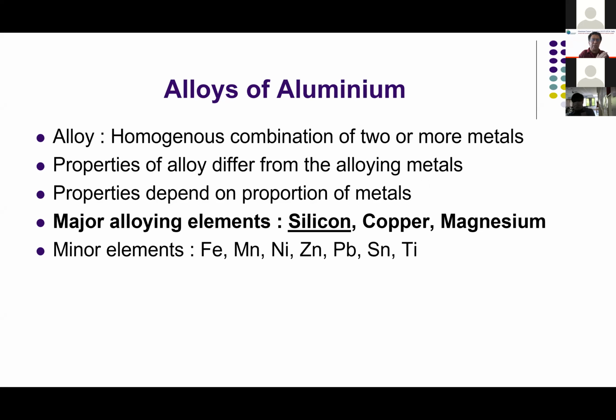When you make an alloy of aluminum, let us say with silicon or copper, it takes some properties from silicon, and the major properties of aluminum are retained, and it forms a third metal with slightly differing properties. Properties depend on the proportion of the metal. Suppose you are adding 3 or 4 metals to aluminum, it extracts different properties proportional to the percentage added. Now, there are two things in alloys. One is the major alloying element, the other is minor. When I say major, the proportion is much more than 1%, up to 20-25%. Silicon, copper, magnesium: these are all major alloying components. Minor elements are iron, manganese, nickel, zinc, lead, tin, and titanium. We also add a little bit of strontium, etc. I will come to that slightly later.